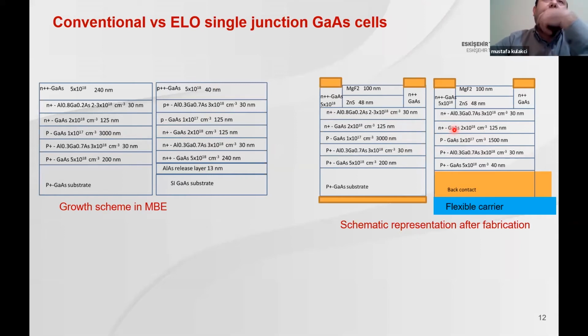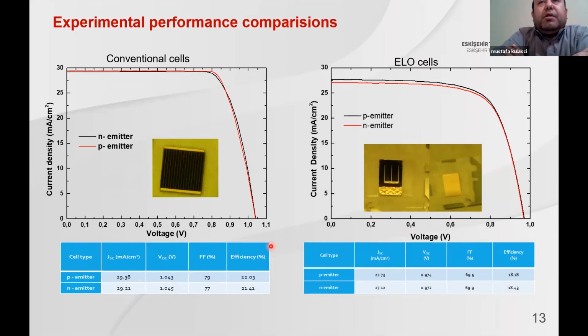the thin film is a bit, 2% higher compared to the wafer-based case, but of course, in our facilities, there is some deterioration in the thin film cases. In the realistic case, when you look, the efficiency is much lower compared to the conventional cells. Here you see the conventional cell efficiency, the highest efficiency is about 22% for p-emitter structure. It is almost close to 21 and a half in n-emitter. For the LO cells, the highest efficiency we get is around 18%, and for p-emitter, and around 18 and a half for n-emitter.